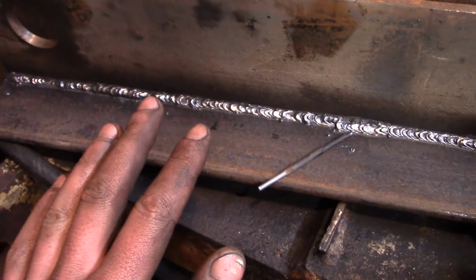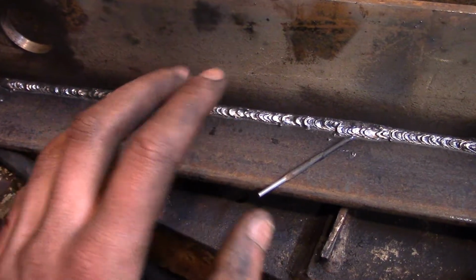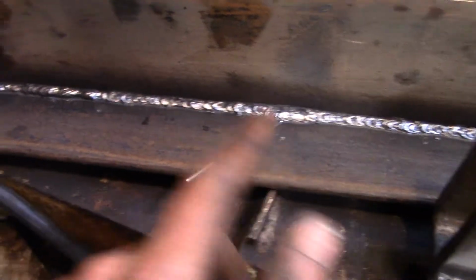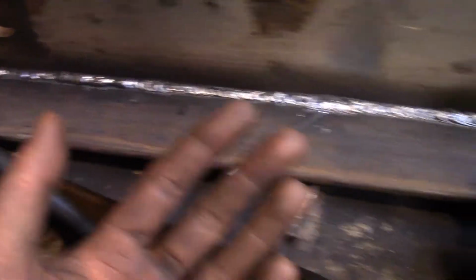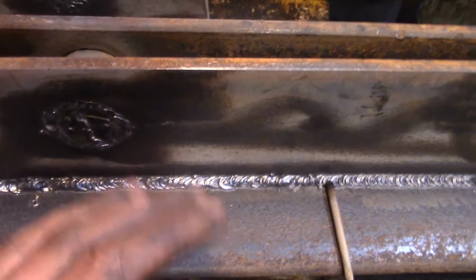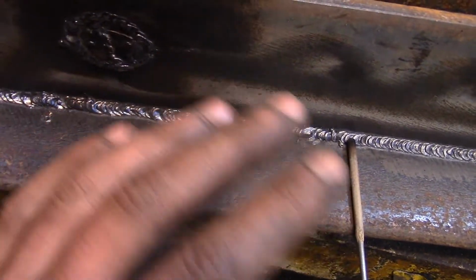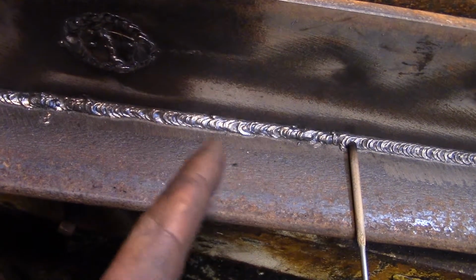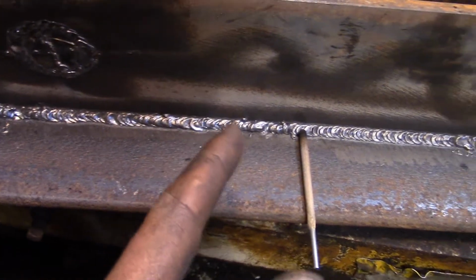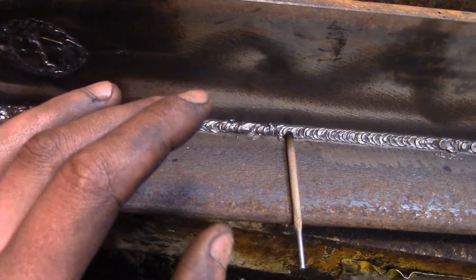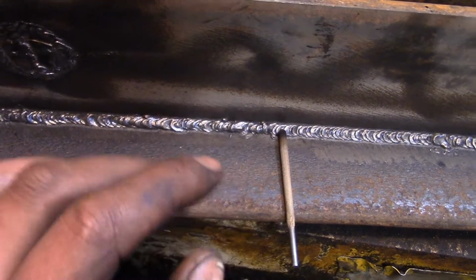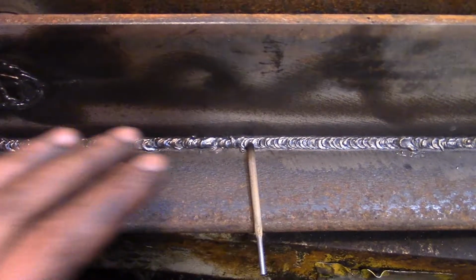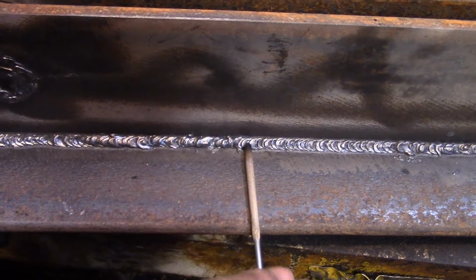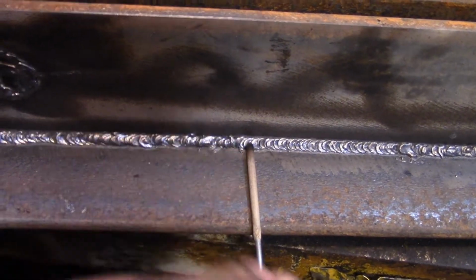And that's because, since I was welding with more heat, the rod was depositing a lot faster, so I had to move a lot faster to keep up with it, otherwise it would just glob up. So I was rushed. With 95 amps, the rod just burned off at a nice slow pace, and I was able to do the whip and pause just like you're supposed to. You let it bead up a little bit, then you whip forward and you go back, and you just weld in a really nice bead. You can keep a nice pace, you're not rushing, and it just runs really smoothly.